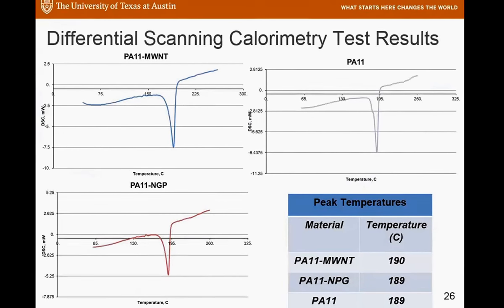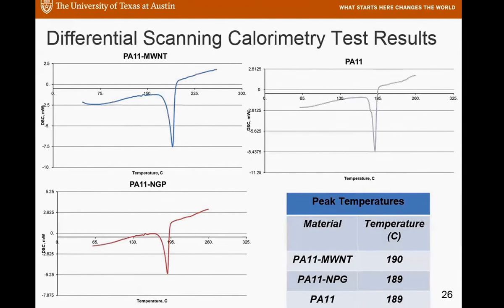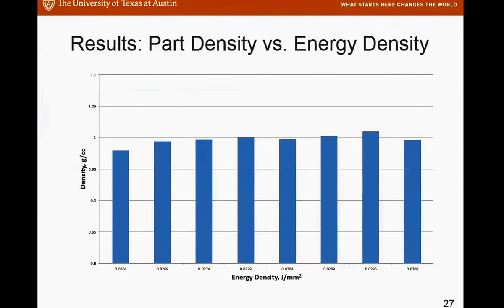and eventually we used this methodology we developed for different types of polymer. Okay, and we also check the DSC and find out these kinds of formulations roughly give you the same window to do SLS, because when you do SLS, you have to see the heating up and cool down in between the 2 peaks. That's your operating window.